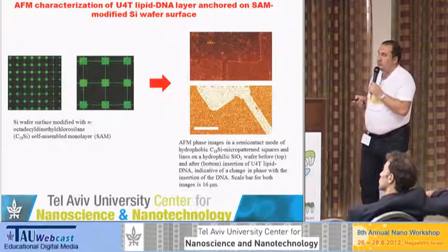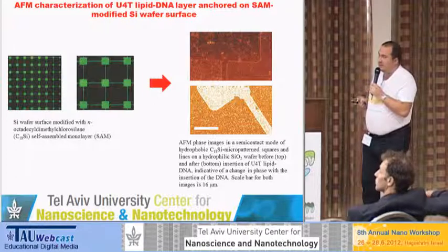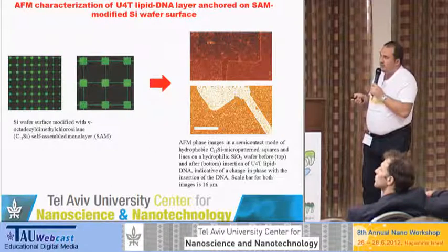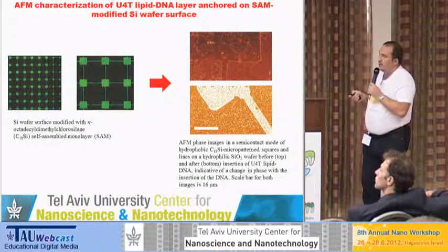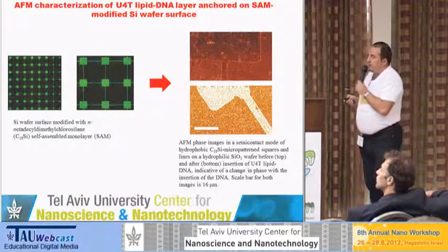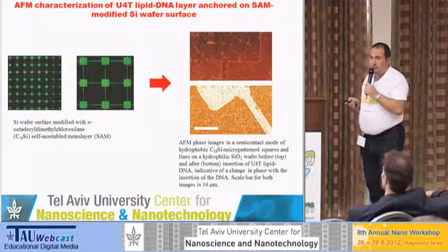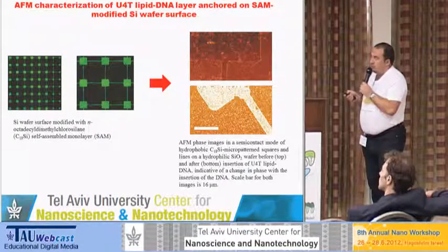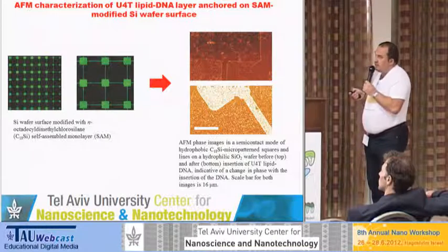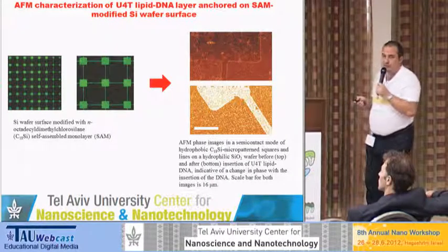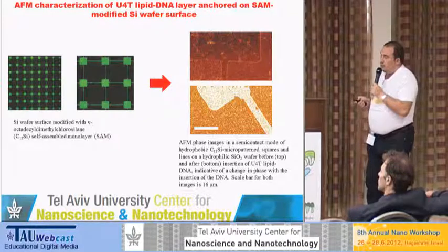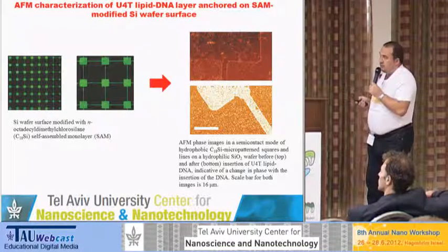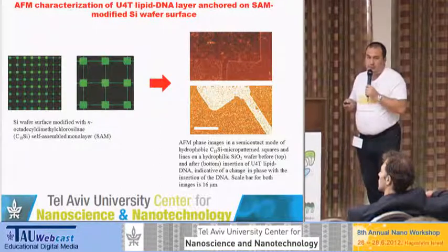Here you see the pattern of the self-assembled monolayers, where you see the green lines and the green squares. They're quite big, it's 30-35 microns. These are lipid DNAs here, and on them we anchor the amphiphilic DNAs. So you see here the phase image of the AFM before and after anchoring the DNAs. So you see here that there is just a hardly seen contrast, but here the contrast is quite prominent. So in this case, it gives additional information about the sample.